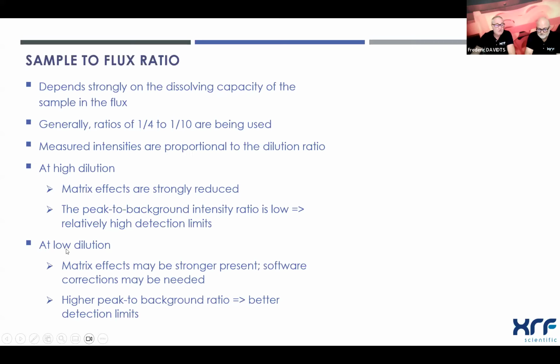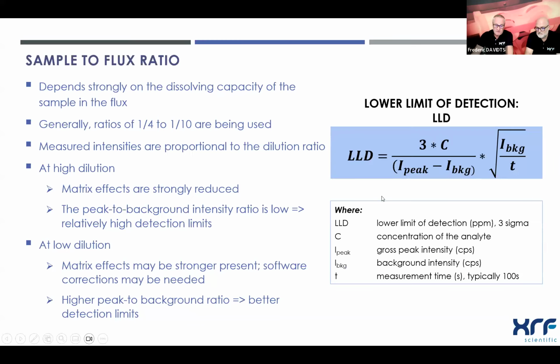And when we have a low dilution ratio, for example 1 to 4, the matrix effects may be stronger and you may have to use the software of the spectrometer to resolve that. But we may have better detection limits. So it's always a compromise. Detection limit is a question that very often comes up, so I give 1 minute of attention to the lower limit of detection.